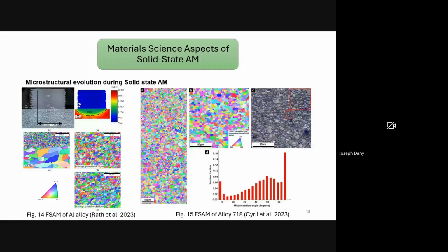In high stacking fault energy metals such as aluminum and nickel, this typically proceeds as continuous dynamic recrystallization, that is CDRX. Subgrains form and gradually rotate and absorb dislocations until low angle grain boundaries are converted into high angle grain boundaries, which produces new, strain-free equiaxed grains. This behavior is exactly what the EBSD images reveal here in figures 14 and 15.